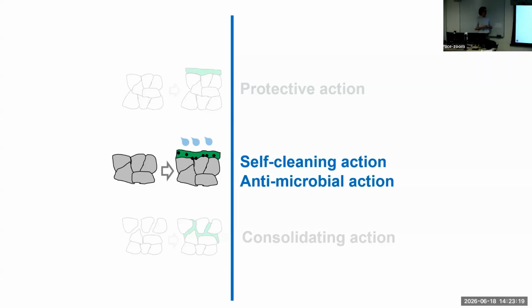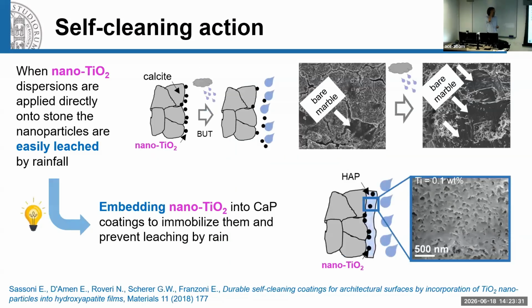Once we found out that we were able to produce these protective coatings, we thought of functionalizing them through some nanoparticles or different strategies to provide some additional action. For instance, self-cleaning or antimicrobial action. Self-cleaning means, maybe you are already familiar with this, the ability of a surface to degrade stains or soiling that forms, for instance, because of the deposition of pollutants onto the surface and so on. This can already be achieved by using nanotitania. Nanotitania is a photocatalytic material. It means it's activated by photons, so by light. So through irradiation with UV light, that's why I put violet here, these nanoparticles are able to activate some mechanism through which they are able to degrade soil, pollutants, and actually also kill bacteria and so on.